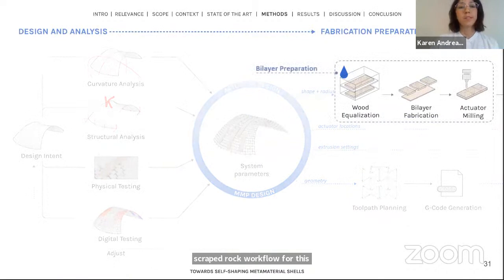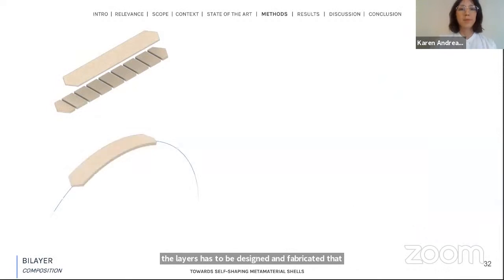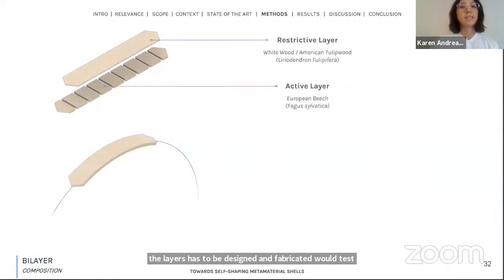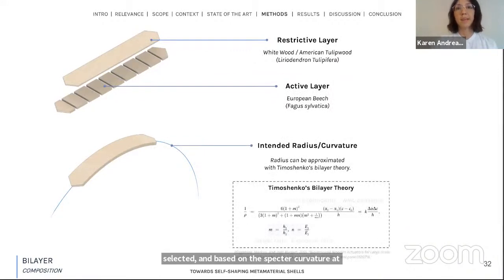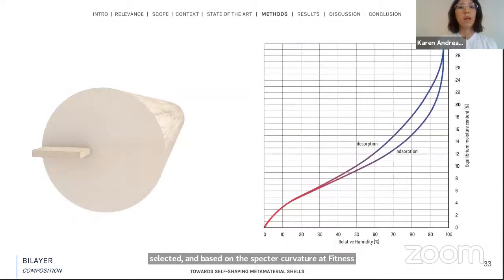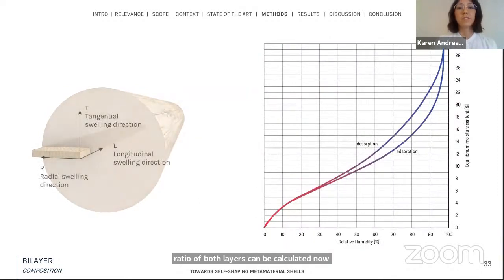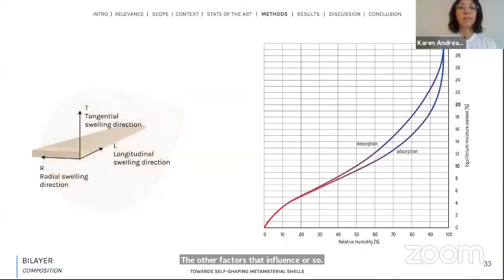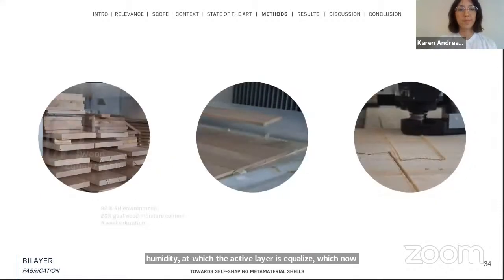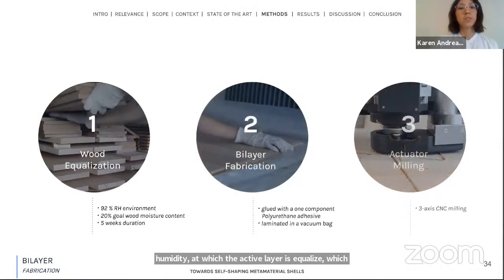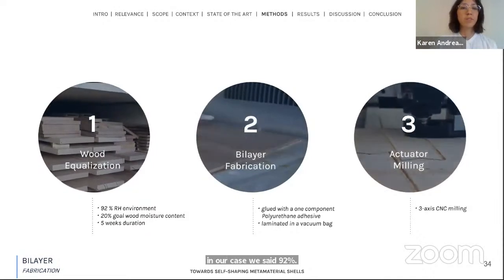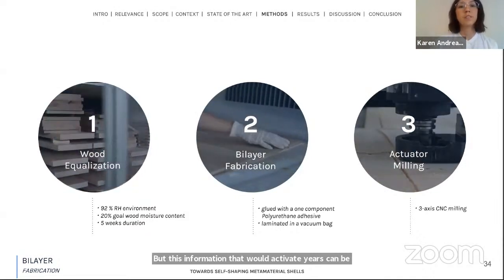For the scaled-up prototype, the bilayers had to be designed and fabricated. The wood types for the active and restrictive layer are selected, and based on the expected curvature, a thickness ratio of both layers can be calculated. The other factors that influence the resulting radius are the grain direction and the relative humidity at which the active layer is equalized, which in our case we set to 92%. With this information, the wood actuators can be fabricated and stored in a humid environment until the start of the